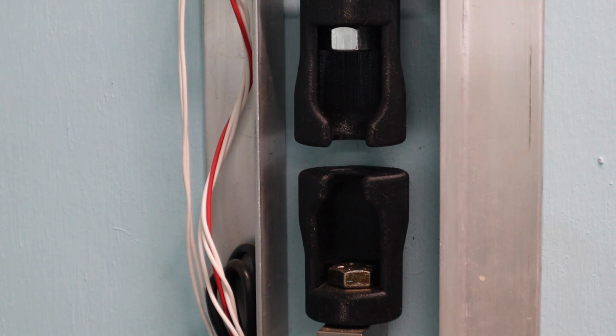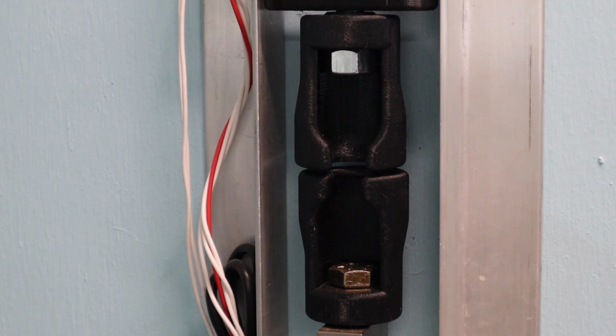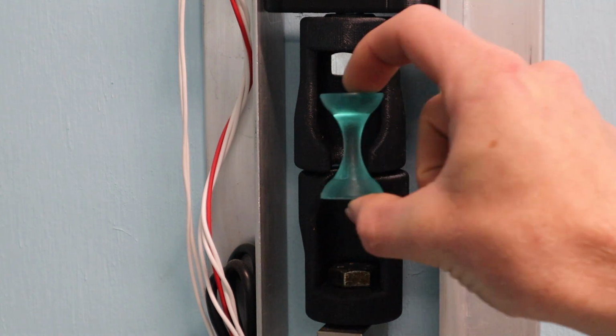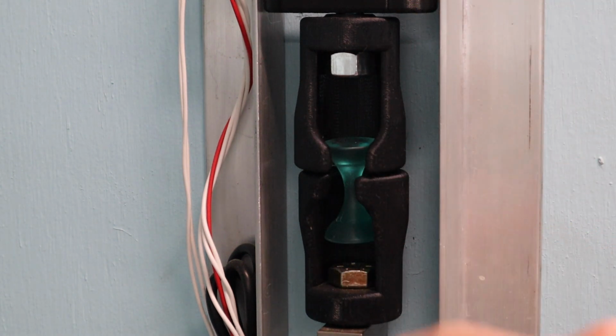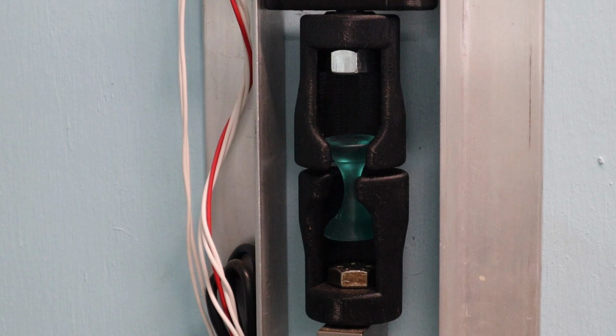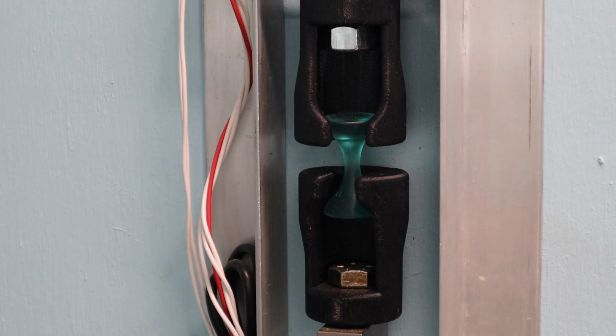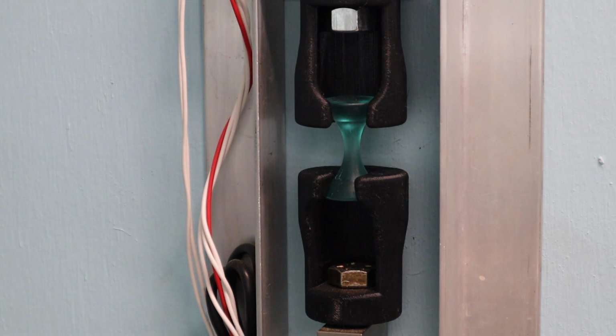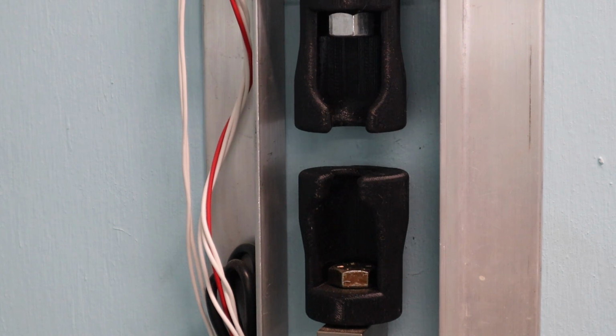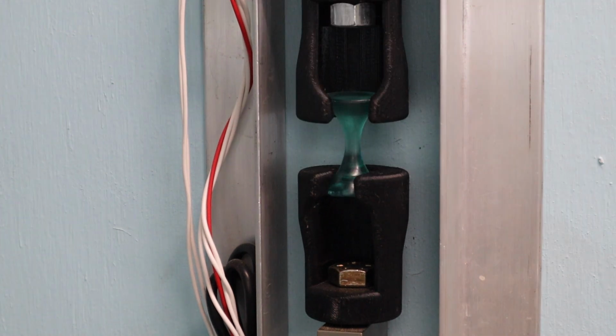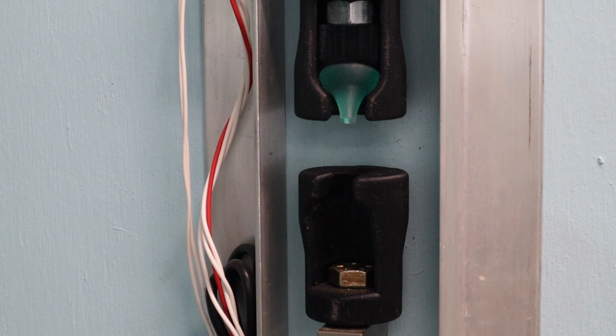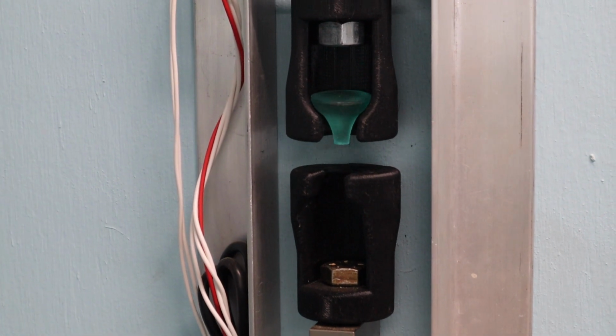Wow, almost 450 pounds. That's all my machine can pull, by the way. So this is getting a little bit on the edge here. It's right on the edge of what I can test with this size of test sample. By the way, the ambient temperature is 75 degrees Fahrenheit. 438 pounds. Let's see. That one broke at 421 pounds.